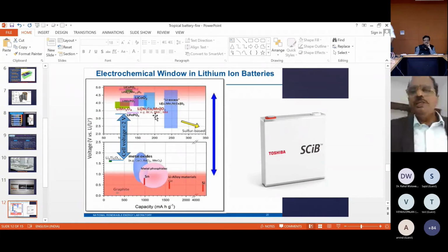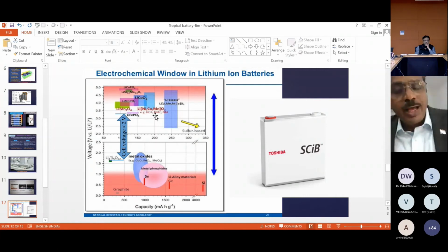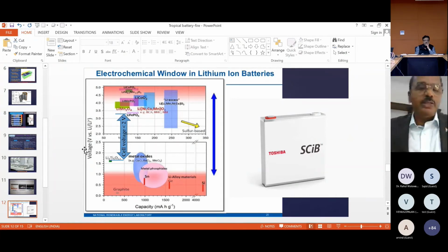If you see the chemistry of the materials used in batteries, this is the voltage on the y-axis. The 0 is the lithium, Li+. That means versus a lithium anode, what cathode do I use so that I get maximum voltage? If I use lithium metal foil, which is 0, and I use lithium iron phosphate, I get 3.2 volts. But if you use lithium, it will blow up because lithium is very, very sensitive to moisture and air. So people use graphite, which is very close to lithium, only 0.5. So you still get 3.2 when you use LiPF6 with graphite, or NMC. NMC has 3.5 to 3.6, so that also will give higher voltage and higher energy density.